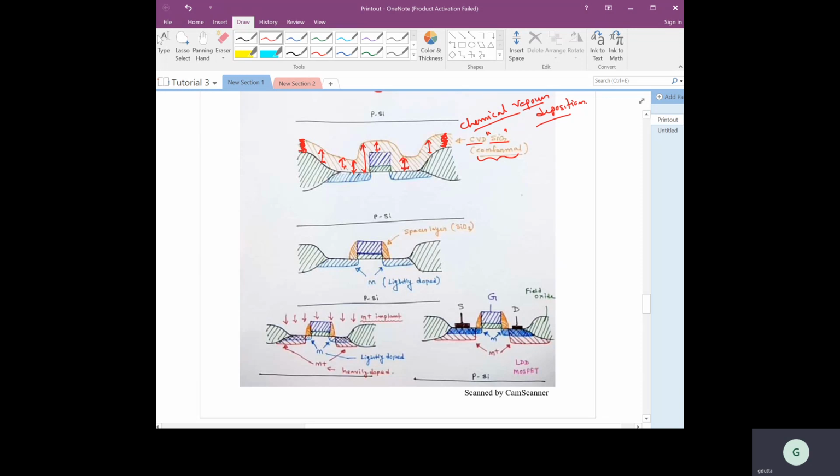So whenever this region gets etched completely, even on the top and the sides, there will be some amount of silicon dioxide left like this, right? Got my point, right? This amount of silicon dioxide will be left from here and here. Now, how are we etching this? We are using dry etching.